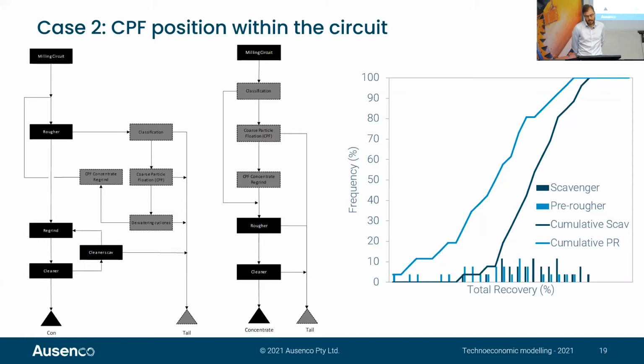And on the graph on the right-hand side, you can see where I did a what-if analysis. I said, what if the recovery by size of the coarse particle flotation was variable? So it's a new technology. What if we start losing the ability to recover, or the recovery drops, and there's variability in that recovery? And what I found is that variability impacted overall recovery to a much greater extent when it was in pre-roughing duty than when it was in scavenging duty. So there's a higher risk of not producing a throwaway tails when it's in pre-roughing duty than scavenger duty. So there's higher risk, and there's also higher capital to have it in that pre-roughing duty.